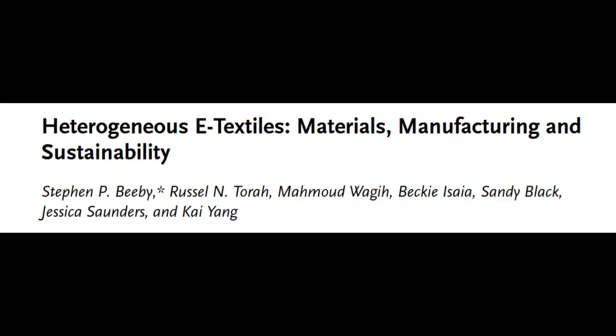What about ways to coat just the fibers you want, selectively? That's where selective metallization comes in, often using something called electroless deposition. Electroless deposition. Okay. The idea is you first apply a catalyst material only to the specific areas of the fabric where you want the metal. You could print this catalyst using screen printing or inkjet. Then, you dip the whole fabric into a chemical plating bath containing metal ions, like copper or gold. The metal only deposits and plates onto the fibers where the catalyst is present. So you get conductive fibers only in your pattern.